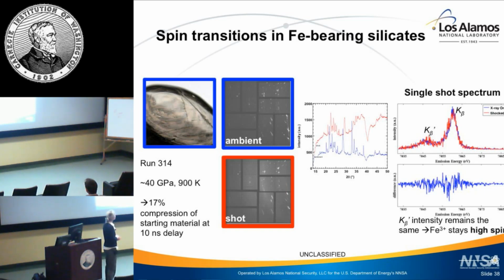In the emission spectra, what do I see? X-ray only is in blue, and then my shot. They pretty much are superposed. If you look at the difference pattern, it's about the same. So we don't have a spin transition. We have compression, but no spin transition. This is at 10 nanoseconds and 40 GPa on the Hugoniot.